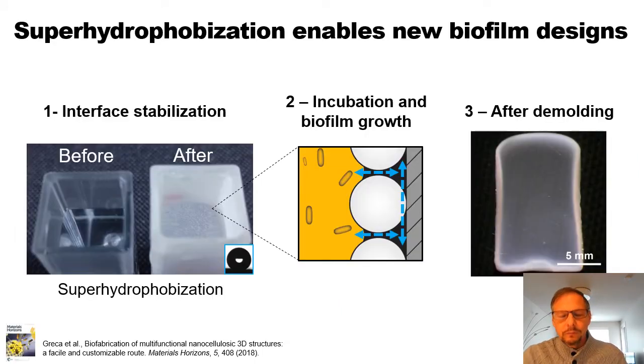So by doing this, by waiting a little bit, we're going to get a pellicle, a biofilm, or a network of cellulose inside the mold, and after separating the cellulose from the mold, it will look like what you see on the far right. So now we have made a cubic or rectangular three-dimensional shape that is based on cellulose. Something that would be difficult to make via typical two-dimensional papermaking processes, right? In this case, you can think of a box.